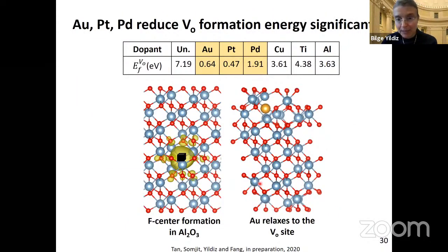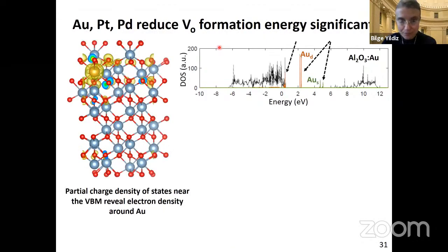So our work here has been primarily computational, which were then verified, validated by our experimental collaborators. And what we are seeing here first is that one can significantly reduce the formation energy of oxygen vacancies if you implant metals like gold, platinum, and palladium into alumina, which is very difficult to form oxygen vacancies alone, right? Because it tries to form F centers, and the energy to do that is very expensive. But if you insert gold, platinum, palladium, which can uptake the electron, the ease of vacancy formation becomes really good compared to other transition metals, which are not nearly as good in reducing the vacancy formation energy compared to high electronegativity elements like gold, platinum, and palladium. So that's point one. We can reduce the formation energy of oxygen vacancies.